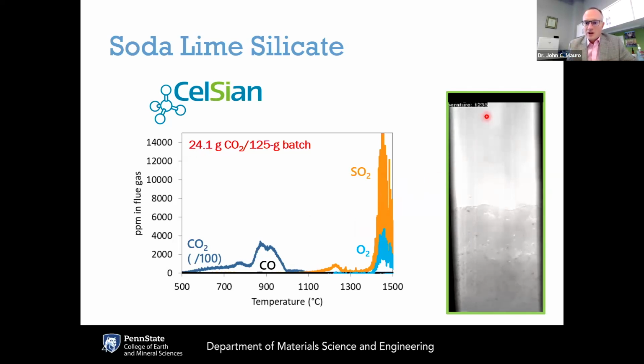And so here, as we get to 1250 degrees C, you can see that there's still a lot more work that needs to be done for melting this batch material and getting a nice homogeneous glass. As we get to 1350, you can see more of the bubbles evolving here. As we get to 1400 degrees C, the fining agent is kicking in.